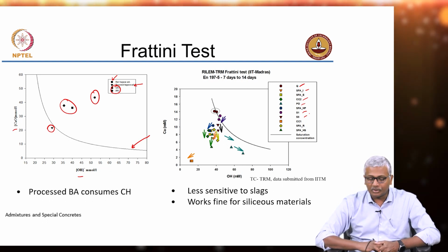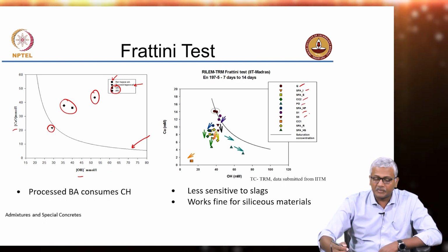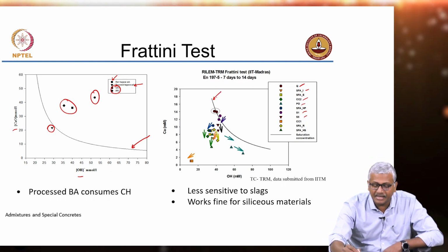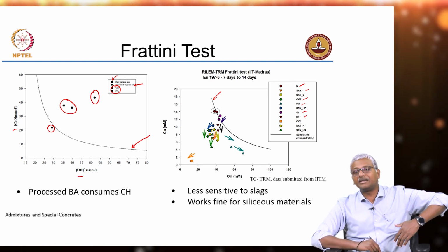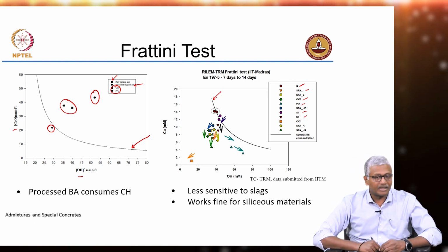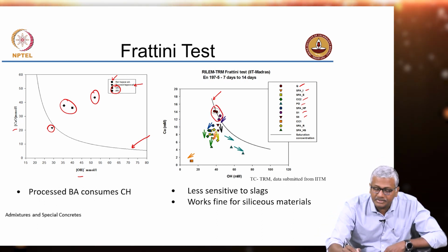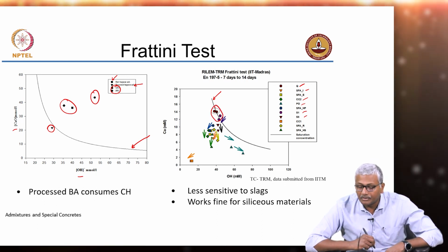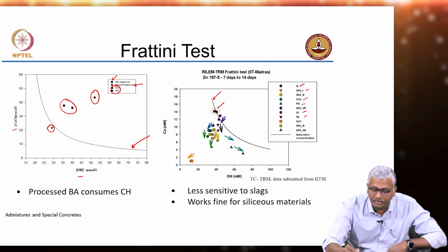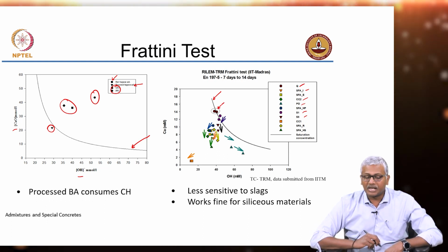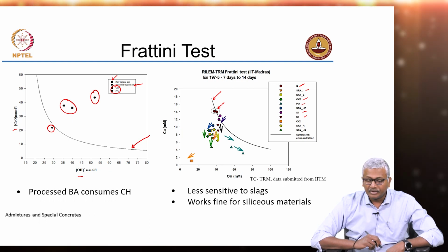And what we saw here was this test method. Obviously, again this is the same solubility curve. So, all the points which are lying below this indicate that your materials are reactive. Interestingly, all your points involving quartz, okay, no sorry, that is not fully quartz, only the top 2 points are quartz, okay. Those are lying exactly on that solubility curve.